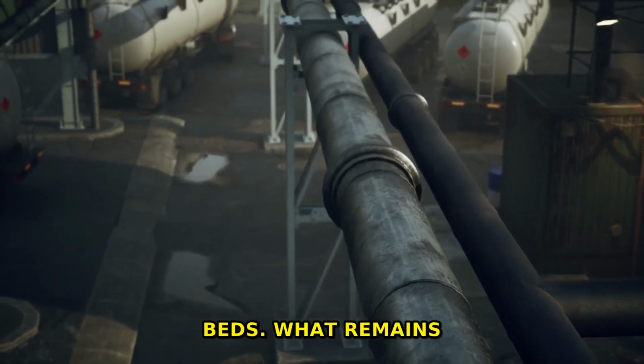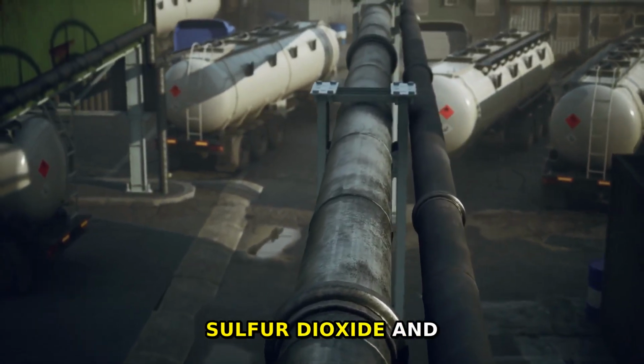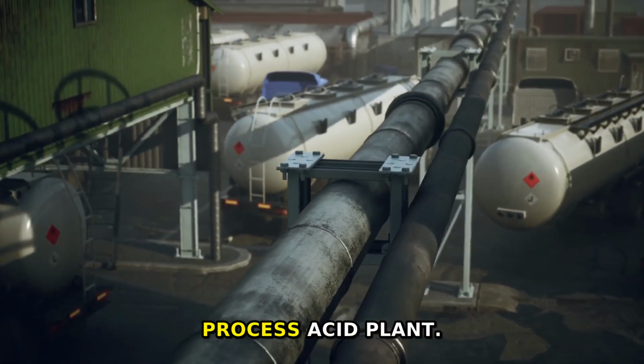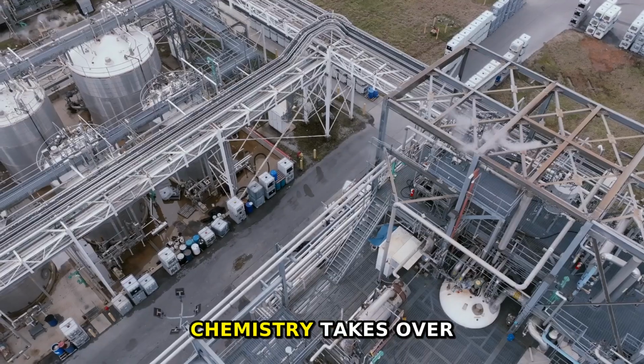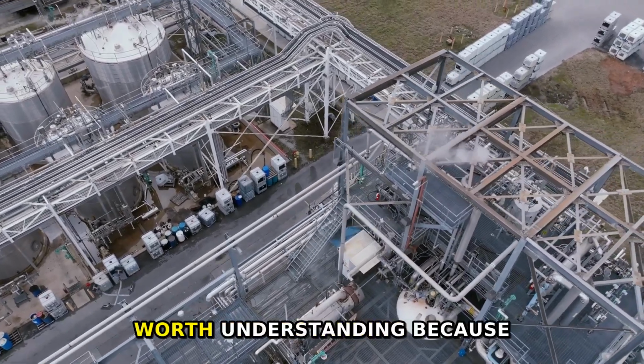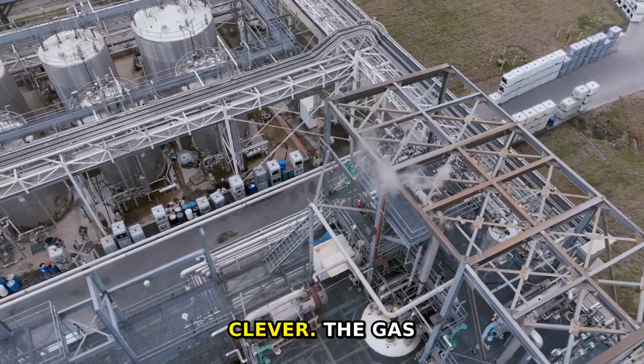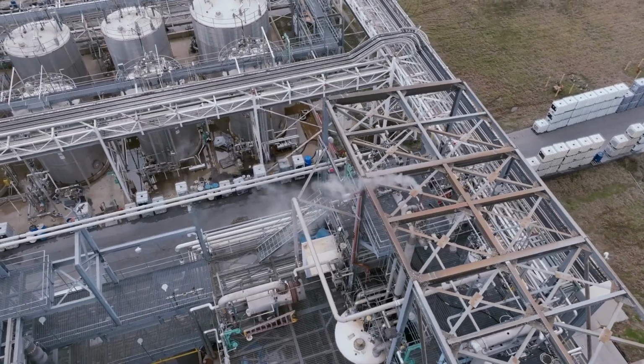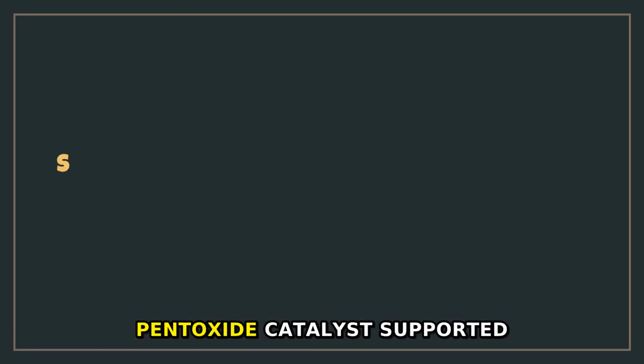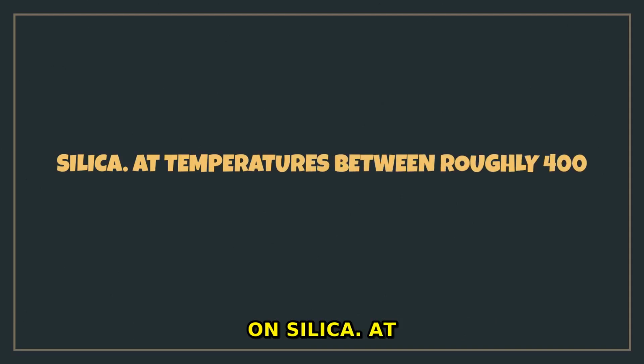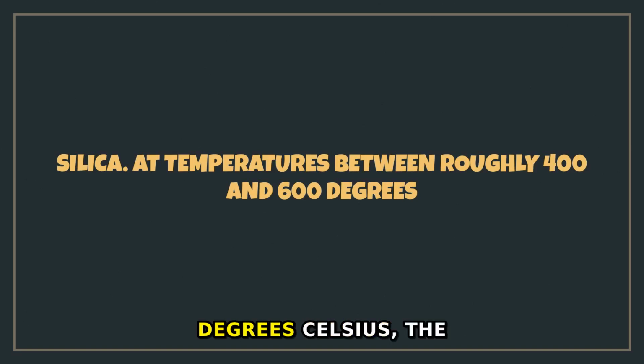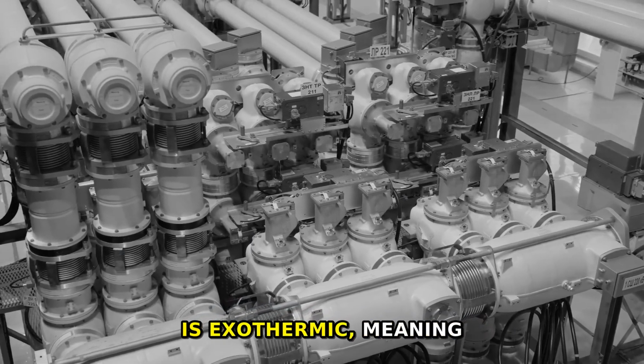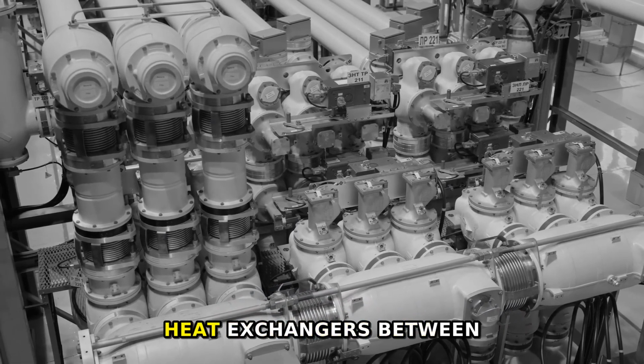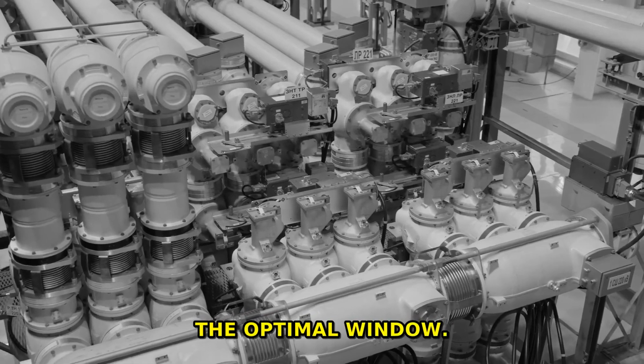beds. What remains is a cleaned, concentrated stream of sulfur dioxide and residual oxygen, moving toward the contact process acid plant. Here is where chemistry takes over from metallurgy, and the mechanism is worth understanding because it is genuinely clever. The gas enters a series of catalyst beds, typically 4 stages, packed with vanadium pentoxide catalyst supported on silica. At temperatures between roughly 400 and 600 degrees Celsius, the catalyst promotes the reaction of sulfur dioxide with oxygen to form sulfur trioxide. This reaction is exothermic, meaning it releases heat, and the beds are designed with heat exchangers between stages to keep the temperature in the optimal window.